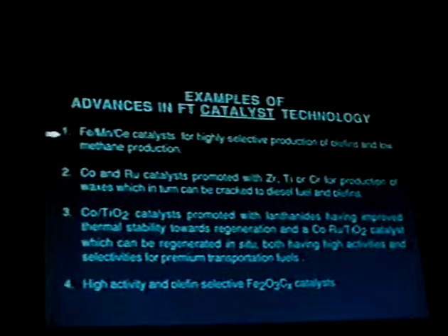They include, for example, an iron manganese ceria catalyst for highly selective production of olefins and low methane make. Cobalt and ruthenium catalyst promoted with zirconia, titania, chromia for production of waxes, which in turn can be cracked to diesel fuel and olefins. A cobalt titania catalyst promoted with lanthanides, having improved thermal stability towards regeneration. A cobalt ruthenium titania catalyst, which can be regenerated in situ, both having high activities and selectivities for premium transportation fuels.